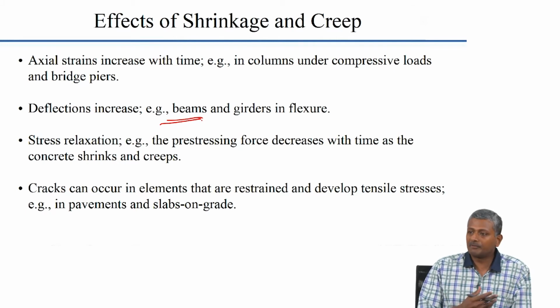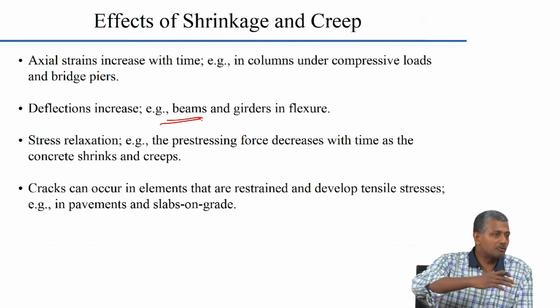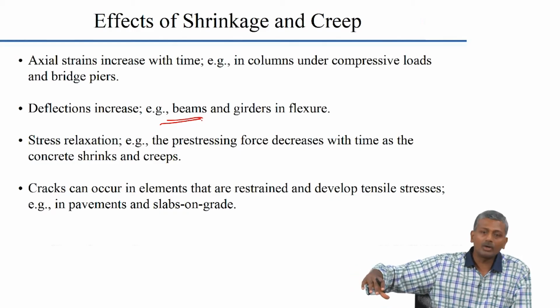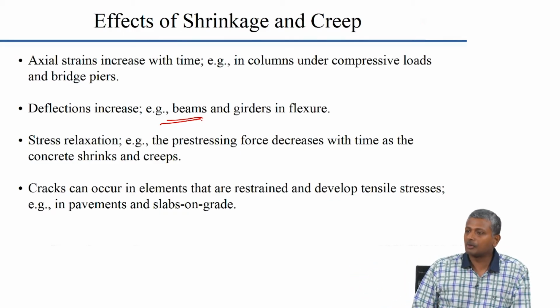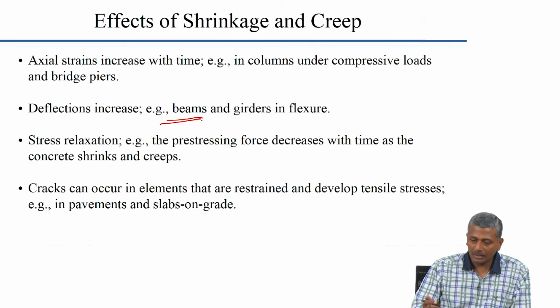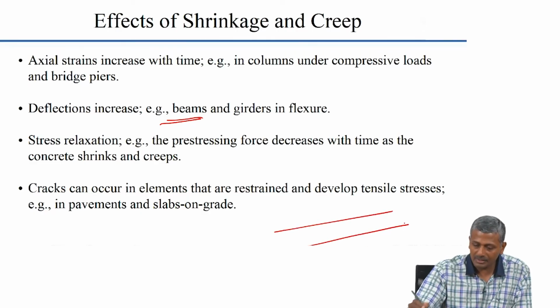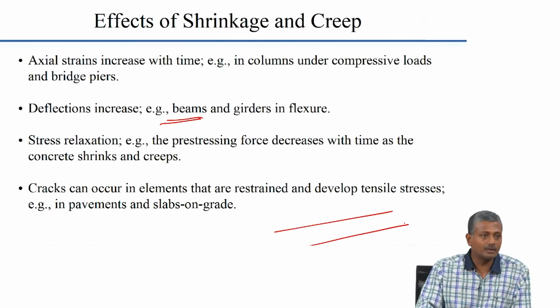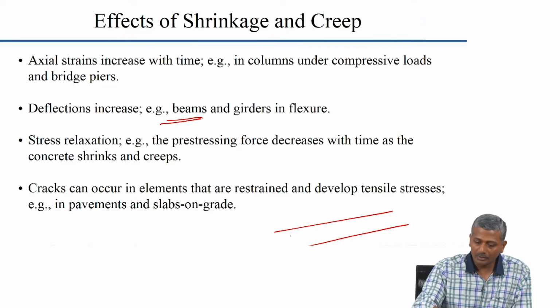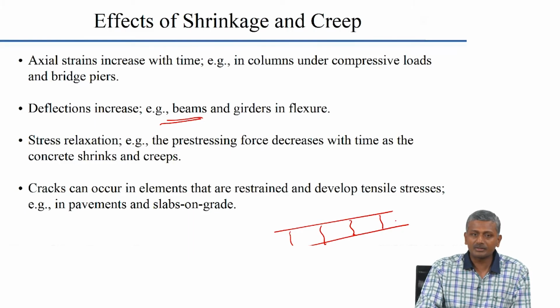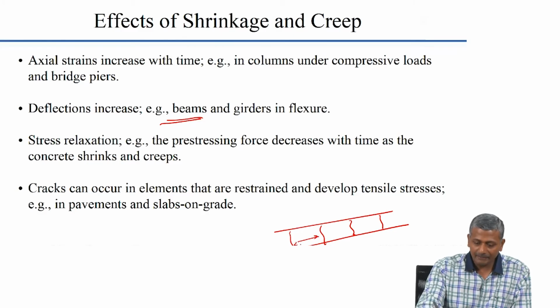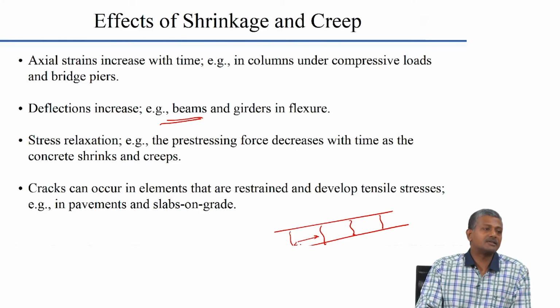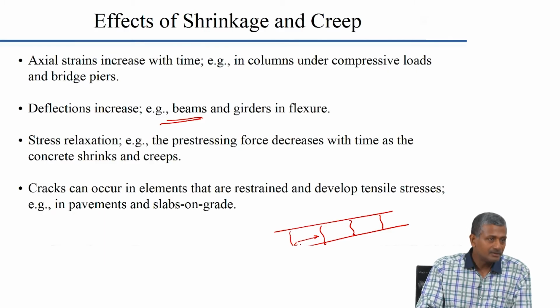Indeed, if you do a pavement which is a continuous slab of plain concrete on top of soil, you let it dry for a couple of days, what happens? What do you observe? If this is your long slab that you put as a pavement on soil, if you let it dry on its own, it will develop regularly spaced cracks. That is because over a certain length, the tensile stresses that are developed due to drying are exceeding the tensile strength of your concrete.